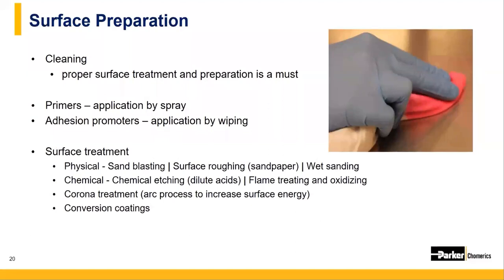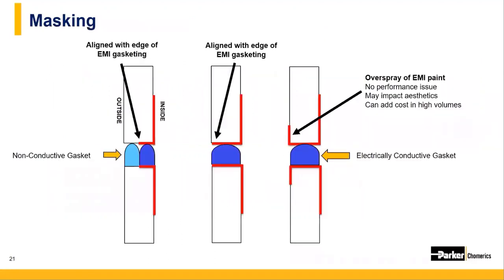Physical surface treatments can include things like sandblasting or wet sanding. Flame treating and oxidizing surfaces, as well as conversion coatings, can help reduce the electrical contact resistance. And finally, as we've mentioned in previous webinars, corona surface treatments or arcing of the material will actually align charged particles on the surface of the material and encourage strong adhesion, but should really only be done very shortly before the application for best results.